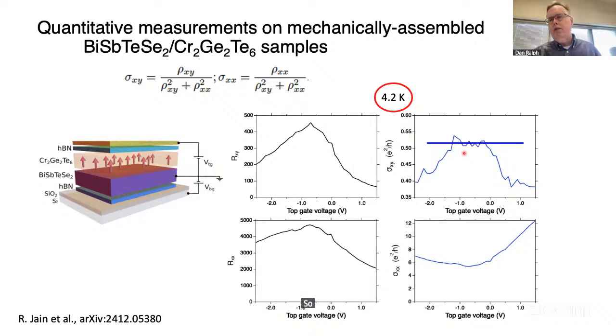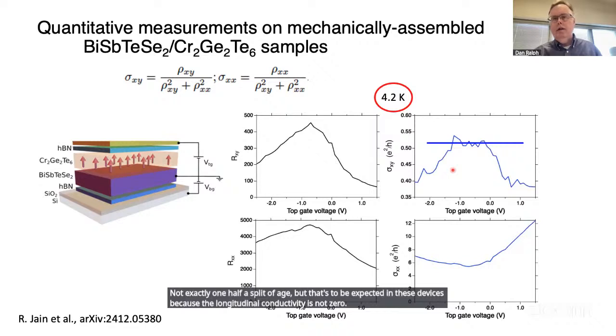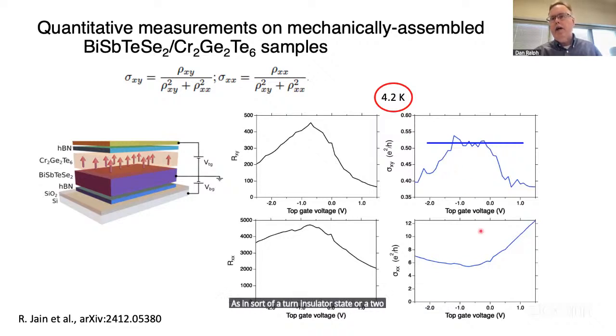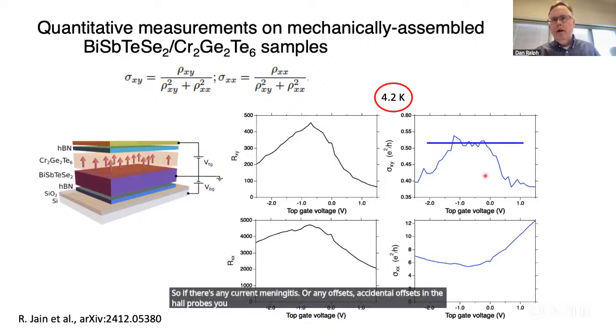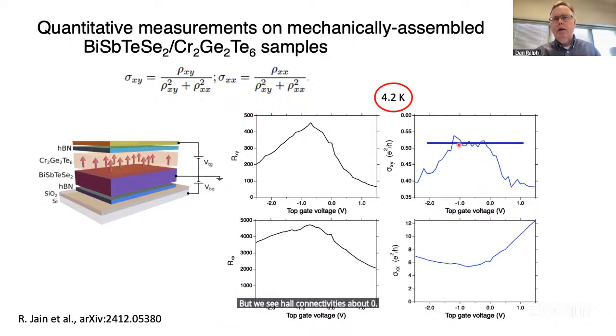So over a range of gate voltage around the Dirac point, you see Hall conductivities very close to 1/2 e squared over h. Not exactly 1/2 e squared over h, but that's to be expected in these devices because the longitudinal conductivity is not zero, as in a Chern insulator state or a two-dimensional electron gas in a high magnetic field. The longitudinal conductivity due to the bottom layer that's ungapped is still here, 6 or 7 e squared over h. So if there's any current inhomogeneities or any accidental offsets in the Hall probes, you'll get a small change in the Hall conductivity because of those effects. But we see Hall conductivities of about 0.51, so within a couple percent of an exactly quantized value. And this is not a very low temperature here, this is just at 4.2 Kelvin.